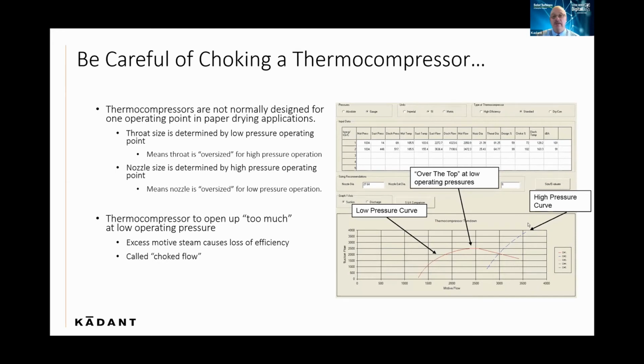One thing we have to be careful with is choking thermal compressors. If that range is too wide between your low pressure and high pressure, it is possible for the thermal compressor to get into a choke condition during a low pressure condition. What we mean here is that the vertical axis is the suction flow, and the horizontal axis is your spindle position or your motive flow. We get up to a certain point where we get to about 2,500 pounds per hour of suction. And then if we continue increasing the motive flow, we start decreasing the suction flow. So we're going in the opposite direction here. We have to be aware if there is a choking condition on a thermal compressor, so that we're not operating it beyond the choke point.